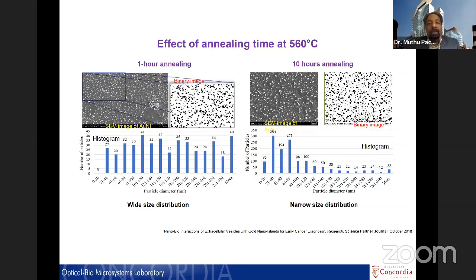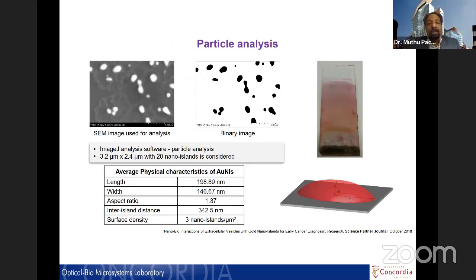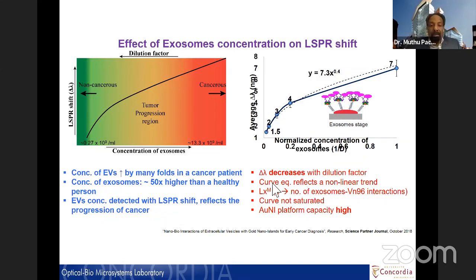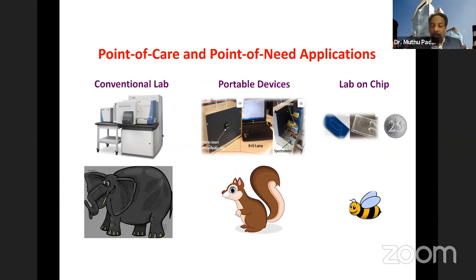The morphology tuning in relation to the biological molecules is very important for this kind of study. You can see the SEM image used for the analysis, and this is the nano island, and these are the final results that we got. You can see very well here that the plasmonic shift, lambda, with respect to the concentration of the microvesicles gradually increases, covering the full range from no cancer to full cancer stages. So we can have a very portable, disposable, cheap diagnostic tool for early diagnosis of cancer through integration with nanoparticles using surface plasmonic properties.